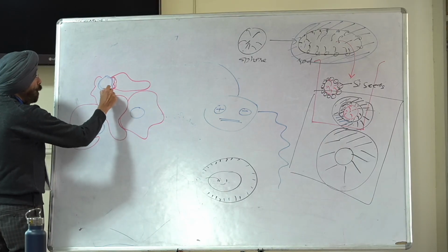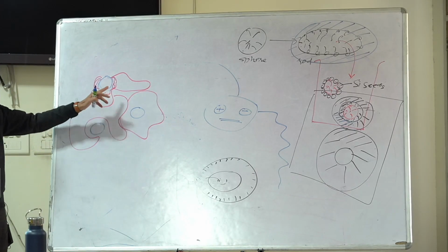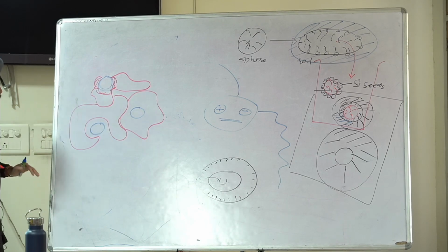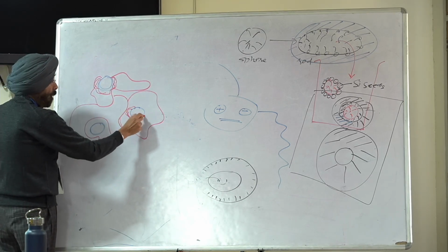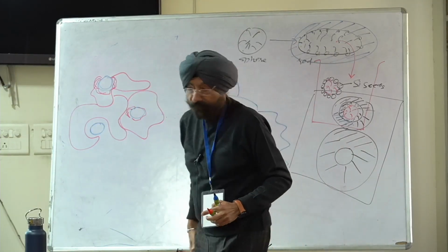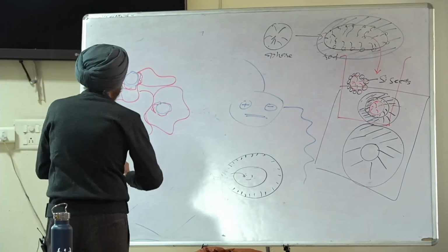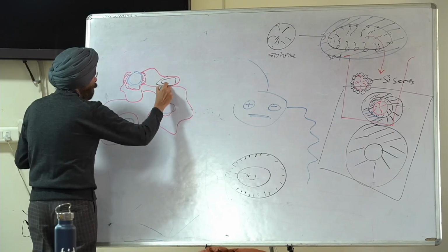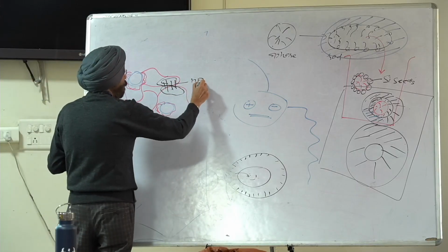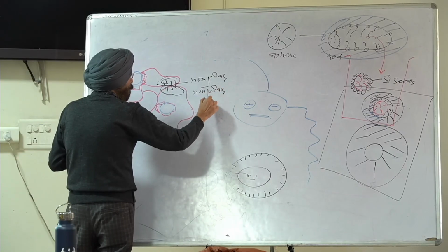So you may expect that this is the hydrophilic domain that is on the surface, acting as anchoring site to attach the protein to the nanoparticle. The same is the story over here. But where are the hydrophobic domains? Hydrophobic domains are away from the surface, and because of the non-polarity, the hydrophobic domains of this protein molecule have non-polar interactions.